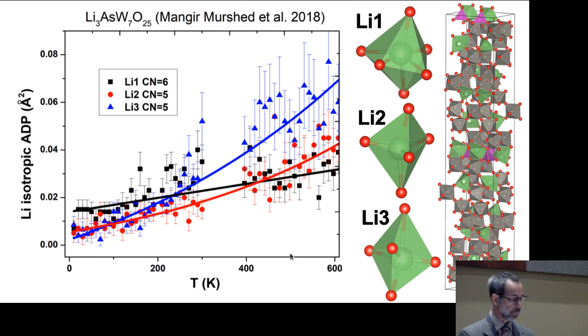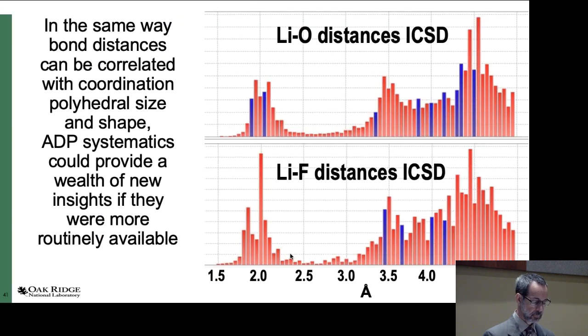Here's another example which I took from the literature. It's a lithium arsenic tungstate. This was using powder data from PowGen at the SNS. I just took their data and replotted the ADPs they determined as a function of temperature to show that the displacement amplitudes and 0 point values can be related to the differences in the coordination polyhedra. There are 3 different ones here. It's 6 coordinated, and these 2 are 5 coordinated.